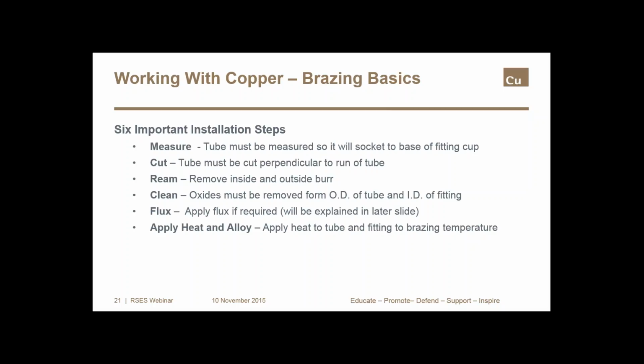Dirt, oil, and oxides that form on the surface of all metals will interfere with the flow of molten brazed alloy, and this flow of alloy is absolutely essential to the quality of the finished brazed joint. Oxides must be removed from the outside of the tube and the inside of the fitting. If flux is required, it's applied to the clean tube and fittings before the assembly is heated to braze temperature.